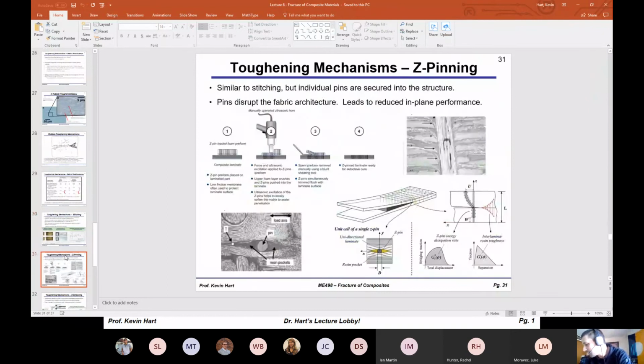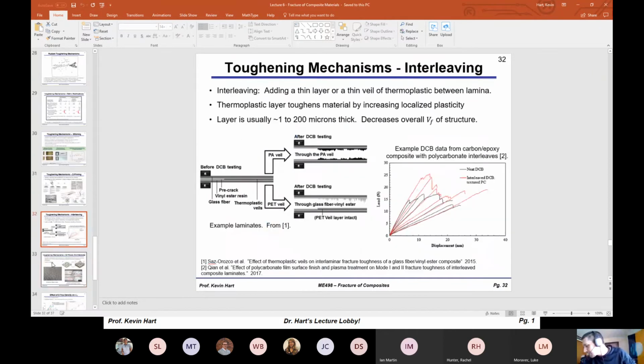We talked about stitching and Z-pinning. Here we had that gun that was driving the pins into the fabric. We see the pins forming inside of the fabric, but we know that these pins disrupt the fabric architecture that's in the plane, so it's not always the best method. Here we talked about interleaving. Interleaving is using a thermoplastic layer between fabric layers to increase the toughness. If you add a very thin thermoplastic layer between the individual lamina layers, then you can arrest crack growth through the plasticity that's involved in that thermoplastic interlayer.